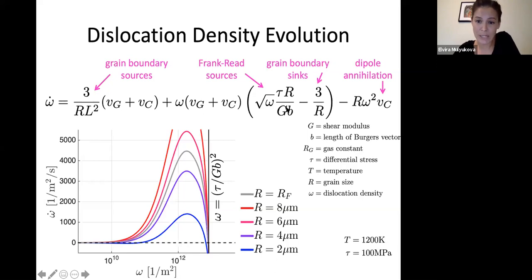So this entire equation is then plotted here. I'm showing you the rate at which the dislocation density increases or decreases through time as a function of dislocation density itself, and I'm plotting it for different grain sizes. What you see here, I'll first explain this grain line, which is the field boundary grain size. Field boundary meaning that at this grain size, the strain rate that is accommodated by dislocation creep is as efficient as the strain rate accommodated by diffusion creep.